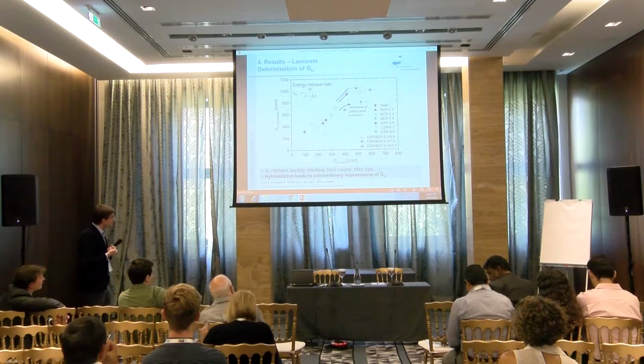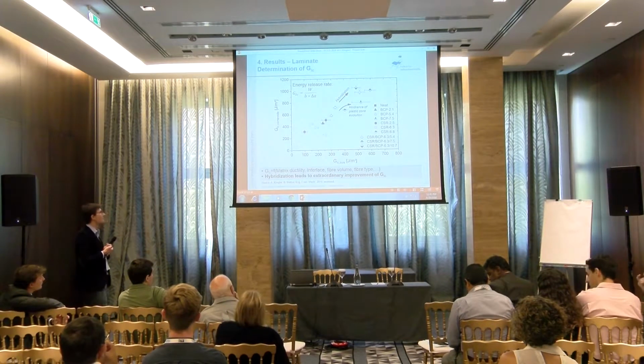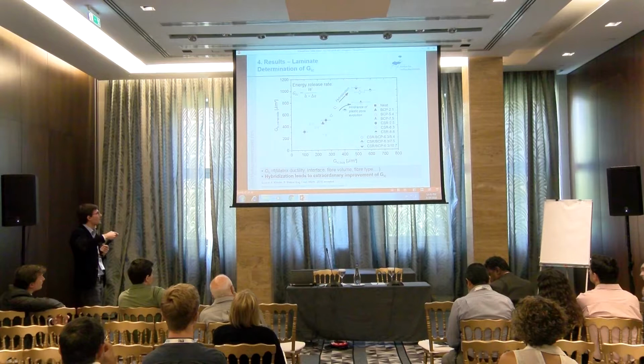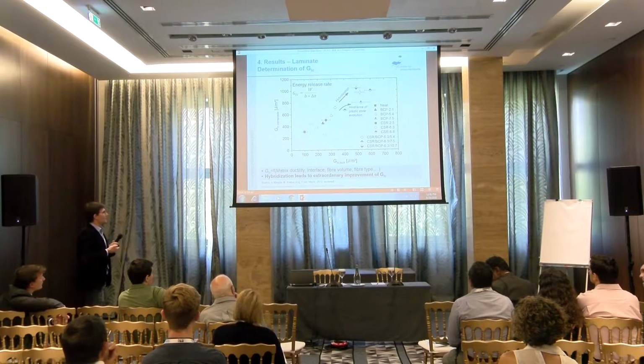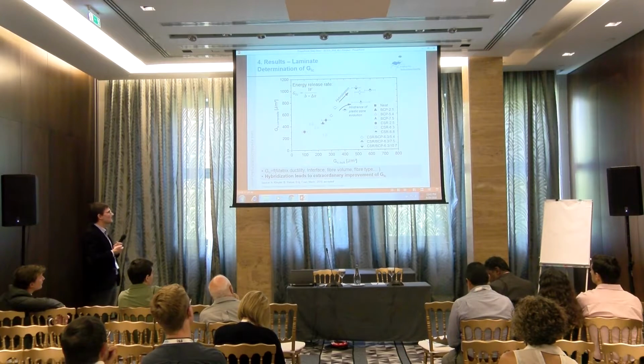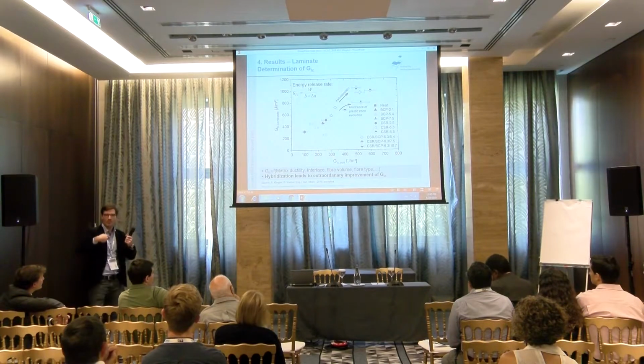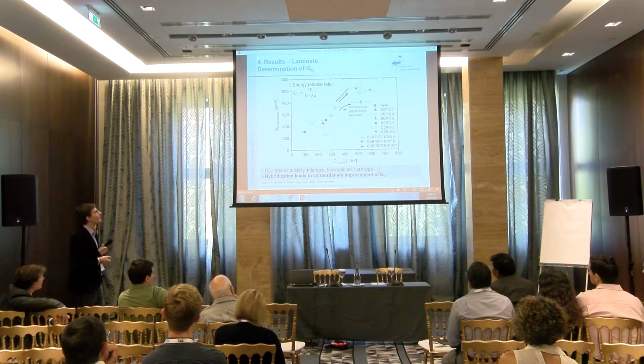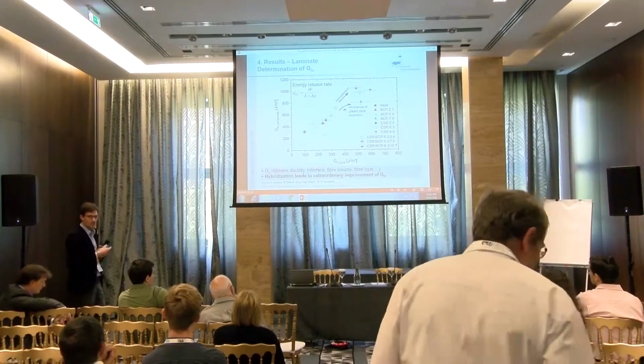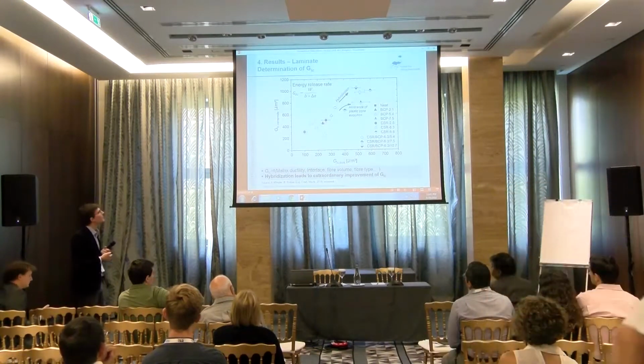First of all, if you take a look at this point, at the neat reference, to better see that, I added those dashed lines so we can follow the kind of excess that you would usually expect. So if we have the neat reference and we test that in the matrix, we get about 100 joule per square meter. If we test that in the laminate, we get an excess of threefold, more or less. And this is related to additional mechanisms, as some of us have learned in the summer school as well, such as fiber bridging effects and so on, which are introduced in the laminate.